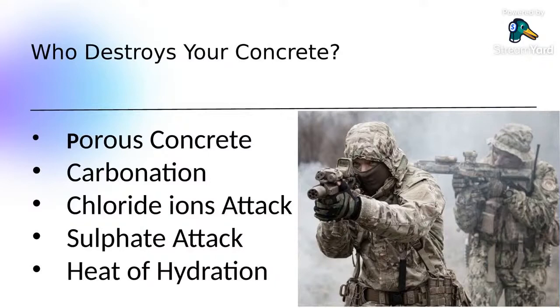So we are always learning, and we are never the great master. We are always students of this great subject of concrete. And today it seems that we can design concrete for more than 100 years, provided you keep the Coulomb value below 800. How you do that is not only use OPC, but along with that, you use GGBFS 70%, fly ash 30 to 35%, microsilica, and reduce the water to cement ratio.